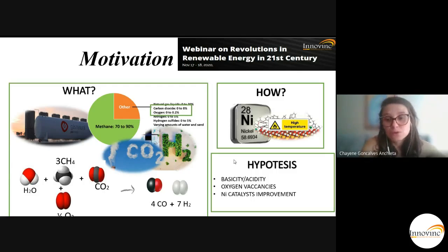Also, we want to improve the oxygen vacancies to get more and more active sites. Nickel catalysts need to be improved, and using support materials that make these catalysts more active is a great issue. And nickel catalysts are supposed to suffer some sintering at high temperature. So we need to change the scenario, looking for stable nickel catalysts.